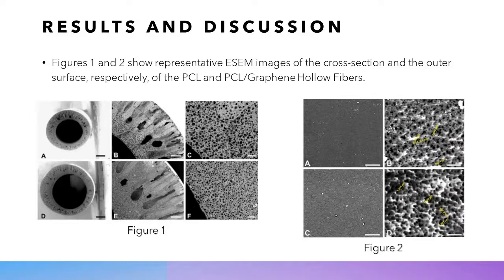From the cross-section of PCL, Figure 1A, and PCL graphene, Figure 1D, hollow fibers with a porous morphology were observed. At a higher magnification, the porous structure of the cross-section of both hollow fibers was asymmetric and contained finger-like cavities or macrovoids, reaching from two-thirds of the wall towards the outer surface, and a sponge-like structure with micropores towards the internal diameter, as shown in Figure 1B, C, E, and F.